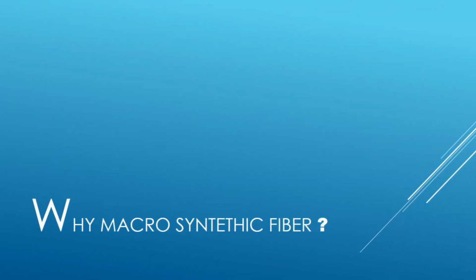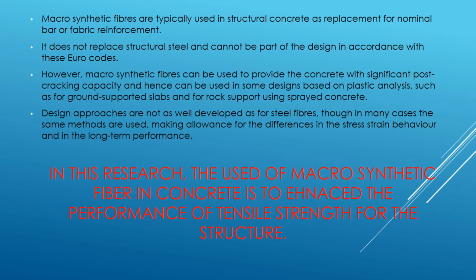Why macrosynthetic fiber in the mix of concrete? Macrosynthetic fibers are typically used in structural concrete as replacement for nominal bar or fabric reinforcement. It does not replace structural steel and cannot be part of the design in accordance with these Eurocodes. However, macrosynthetic fibers can be used to provide the concrete with significant post-cracking capacity and hence can be used in some design based on plastic analysis, such as for ground-supported slabs and for rock support using spray concrete. In this research, the use of macrosynthetic fiber in concrete is to enhance the performance of tensile strength for the structure.